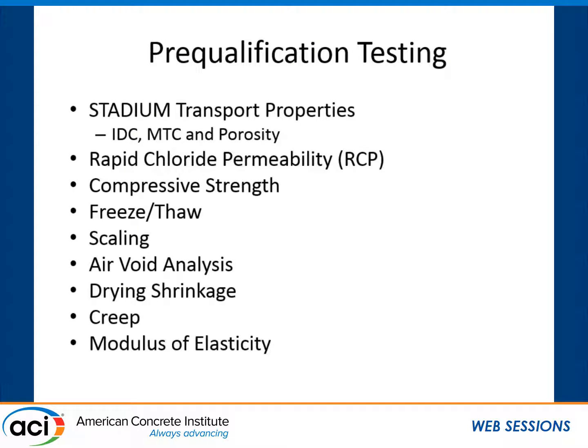Now the pre-qualification testing would be, they need to provide the data on the transport test on each of the mixes. The rapid chloride permeability, so we can have future correlation of the transport test and also the RCP test. Then the compressive strengths, the freeze-thaw, the scaling, a lot of the tests that you want to have to prevent cracks, like the shrinkage issues and the like. The designer and the contractor together tend to team up pretty well to try to eliminate cracking as much as possible. It doesn't do anybody on that team any good if they didn't. So they try to do their best to minimize that and use the right materials to have the other durability concerns taken care of.